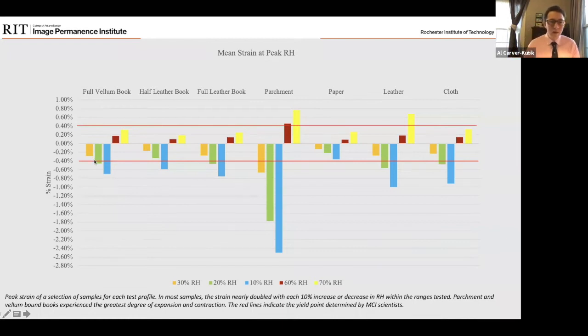These red lines represent the yield point determined by the scientists at the Smithsonian. And so this is the one where they said, if you hit 0.4% strain, you will likely experience permanent deformation. But as I said, when we hit these sort of extremes, 20%, 10% relative humidity, again, the 30% and the 60% are within what we consider the safe zone, like what's acceptable for relative humidity for most collection materials.